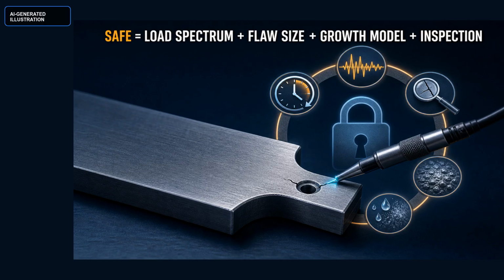So the honest sentence is not, every load is safe, therefore the crack cannot grow. It is, for this material, geometry, surface, environment, initial flaw size, load spectrum, crack growth model, and inspection probability, the crack remains below its critical size for the required interval. Design reduces the local concentration. Manufacturing controls defects and residual stress. Inspection looks where the first crack is likely to hide. Repair or replacement changes the load path. A safe load is a property of that whole system and of how often you check it, not of one number on a static test.